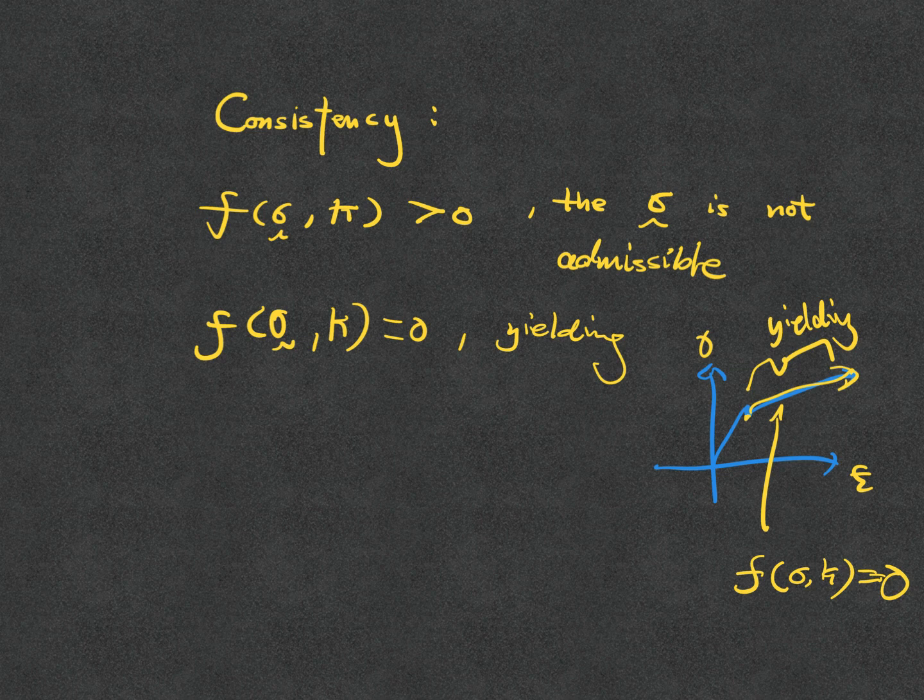So what happened is that we also demand that F dot, as a function of sigma and kappa, also equals 0. Does that make sense? Okay, because in this whole region, F is supposed to be equal to 0. So that means F never changes, right? If something is equal to a constant in the whole region, that means it hasn't changed. If it changed, then you have a rate of change, right? If the curve is smooth. So F dot equal to 0 is called the consistency requirement.